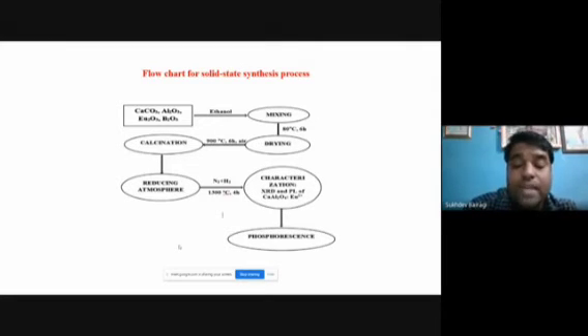The stoichiometric composition of calcium carbonate, aluminum oxide, and europium oxide with different concentrations of the dopant were taken and mixed thoroughly with ethanol in the agate mortar for about 2 hours. And the mixing was carried out at 80 to 100 degrees in the air. The dry powder obtained was calcined, as you can see in the flow chart. And finally the powder was annealed at 1300 degrees Celsius for 4 hours in a reducing atmosphere.